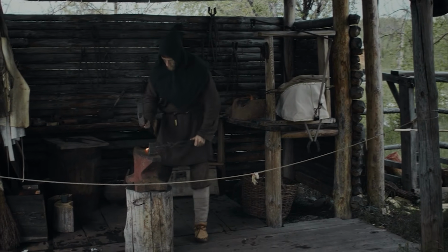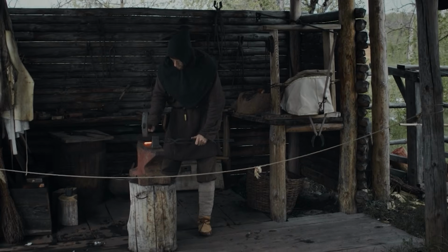They would gently reheat the blade and watch colours spread across the polished surface. Pale straw yellow, deep bronze, peacock blue, purple. These colours were not decoration. They were an exquisitely precise temperature gauge, caused by the thickness of oxide layers forming on the steel surface. Each colour corresponded to a specific temperature, and each temperature produced different material properties.